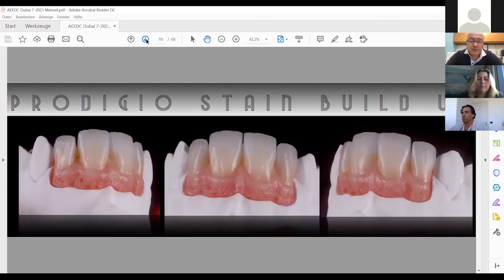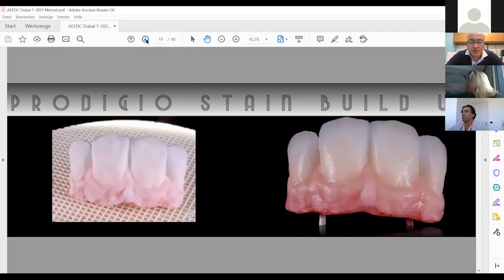Final work. You decide to glaze it. Sometimes I don't really glaze. I prefer to do mechanical polishing. It's a manual polishing with the diamond paste that is also available in the kit. They are really nice diamond pastes that you can use. You can make a very nice, smooth surface with brightness and brilliance of the porcelain as well. Next. So the final bake: if you really need to do any correction, you can. In this situation we use a porcelain, but I will show you later we can use a stain buildup. Next.